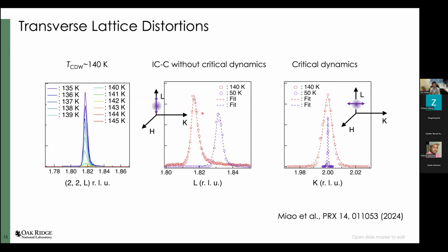When you're cooling down, the commensurate energy will dominate the condensation energy, and then you will change from an incommensurate wave vector to a commensurate wave vector. So this is fully expected. But if you look at the X-ray scan in the AB plane, then you start to see a dramatic change, where at low temperature the peak width is very, very narrow. I think it's resolution limited. But near the transition temperature, the peak becomes significantly broadened. So that means the critical dynamics is really from the transverse lattice displacement.